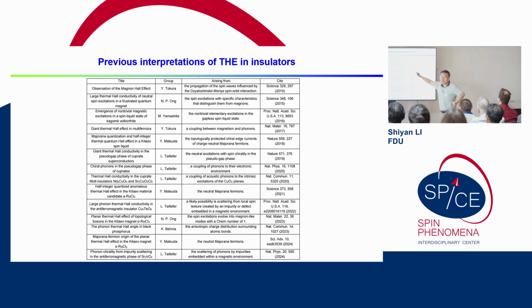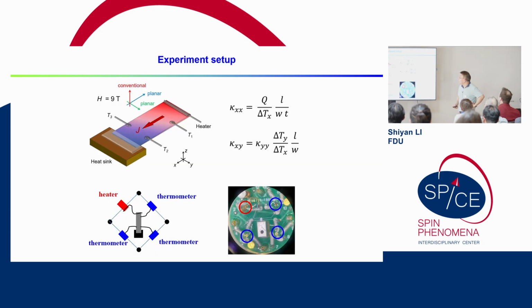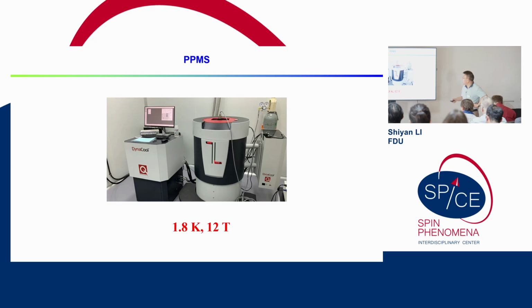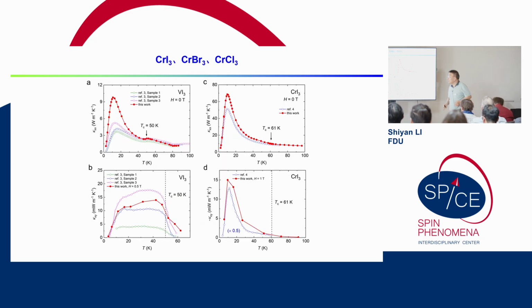So if we put all this stuff together, you can see there may be 20, 30 compounds. Every time you measure it, you find those thermal Hall signals, and you give some explanation, most of the time a very exotic explanation. Then several years ago, in my group we built this experimental setup for thermal Hall measurements, our PPMS. But at the beginning, we didn't have a clear idea how to resolve the puzzle of all these materials. We only tried to measure this series of magnets to compare them and find some difference.